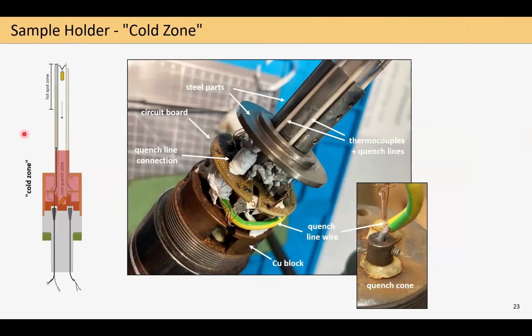And in the cold zone, so located above the closure head, this has first the purpose of providing with this copper block a base for the cold zone, so for the quenching. So when the capsule falls here on the inside on this copper, it will cool quite rapidly, thereby allowing quite fast quenching rates. And secondly, the cold zone is also there to allow us to connect the incoming wirings from the closure head with the upper-lying thermocouples, quench lines, etc. So it's mainly the connection piece of the electrical signals.